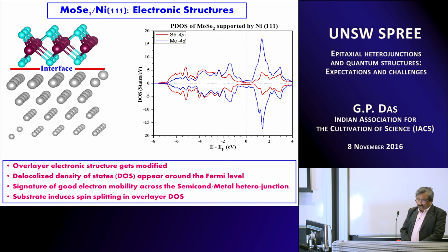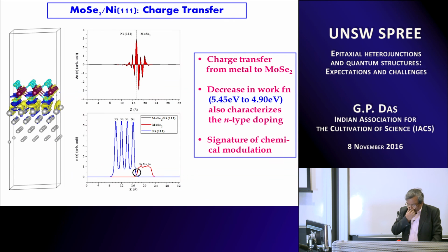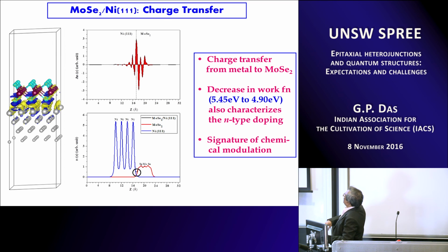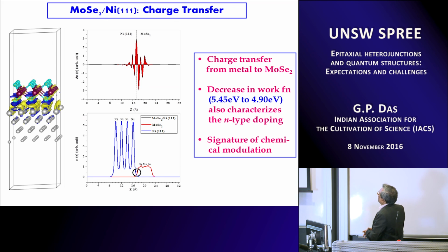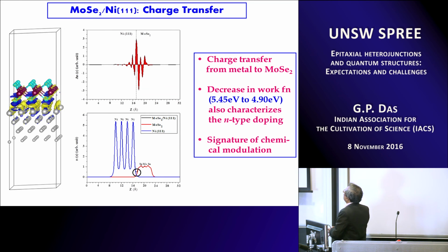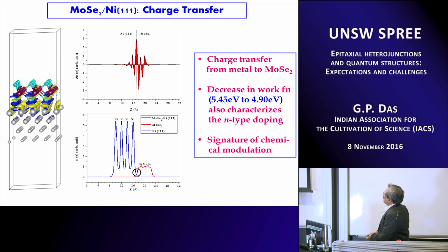And there is also a substrate induced spin splitting in the overlayer density of state which we have found. So obviously there is a charge transfer, and in this case the charge transfer is from the metal to the TMDC, the transition metal dichalcogenide, and there is a decrease in the work function as soon as you put the substrate. From 5.45 eV it goes to 4.9 eV, okay, and this is also characterized by the N-type doping and is a signature of chemical modulation.